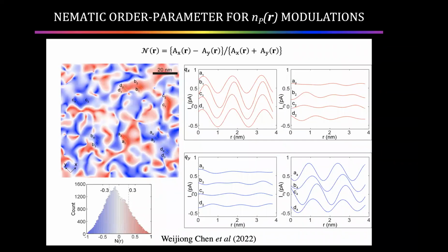So what this tells us is that this is a predominantly unidirectional modulation in the Josephson critical current squared. That would be most consistent with a unidirectional pair density wave, which is otherwise disordered probably by dopant atoms or impurity atoms or something like that. That's what would be breaking it up into this strange state where you have the two Ising domains with fairly long coherence lengths, but not infinity. And this, again, is near 17%. So we're nowhere near the high order region of the phase diagram.